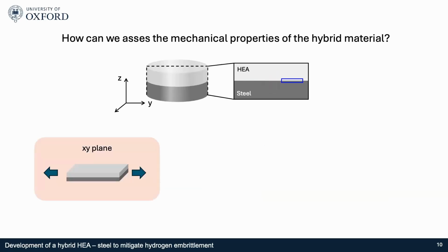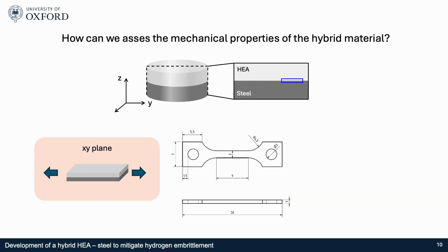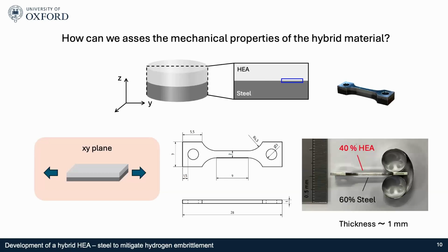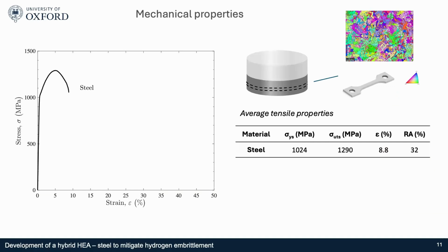So we extracted the specimens from the samples with these measures, and we obtained this, an example of one of the specimens. Then we reduced the thickness to 1 millimeter, having 40% high entropy alloy and 60% steel in all of the samples. First we started analyzing the mechanical properties of each material separately, then to compare with the hybrid material.